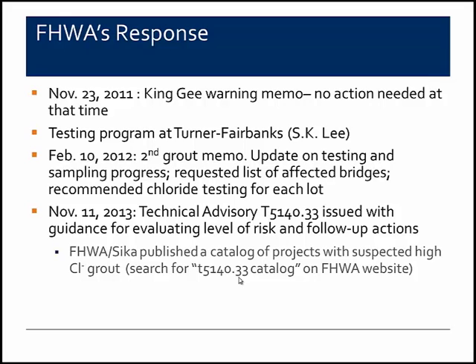And then finally, about a year after the first, or 2 years after the first memo, they issued this technical advisory that now gave results of the testing and a protocol for evaluating the level of risk and follow-up actions for bridges, but this can also be applied to other post-tension structures as well. And then in conjunction with that, FHWA and Sika published a catalog of projects where they suspect the high chloride contaminated grouts went to. And so you can do that search on the FHWA website and it'll pull up the catalog for all the states where they suspect they ship grouts.